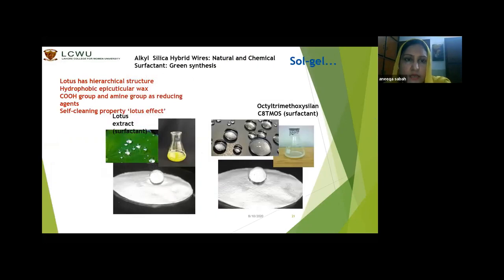Recently, we have worked on alkyl silica hybrid wires using natural and chemical surfactant - that is the green synthesis. The green synthesis is less hazardous because we are using a natural biomaterial, which is not dangerous for us. We used the simple sol-gel technique. The lotus leaf was used, its extract was done, and then using the sol-gel technique we got a hydrophobic layer. Lotus has hierarchical structure, hydrophobic epicuticular wax, COOH group, and amine group as the reducing agent.